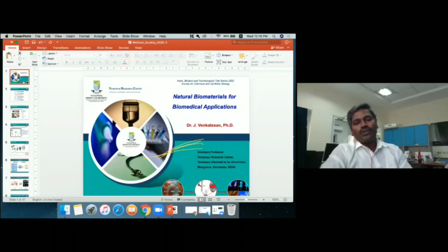What we are working on in biomaterials right now is this first level, only skin. So we are developing the skin. In that case, we have to consider the porosity, the compressive strength, flexural strength, tensile strength, mechanical strength, water uptake and retention ability. Apart from that, it has to induce some genes like collagen 1 and TGF beta, some genes it needs to interact with. So these are the parameters we need to consider.